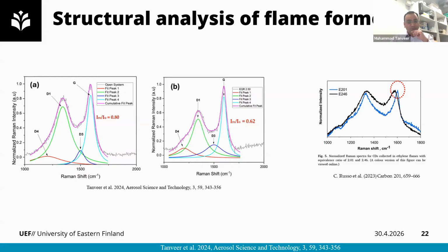in the case of the open system. In the case of the closed system, we have observed a little shift from the normal peak of G. Normally, this G peak appears around 1580, but in our case, it is around 1600. This shows the interplay of OC and EC fragments. That's why it is shifting from its normal position to 1600.